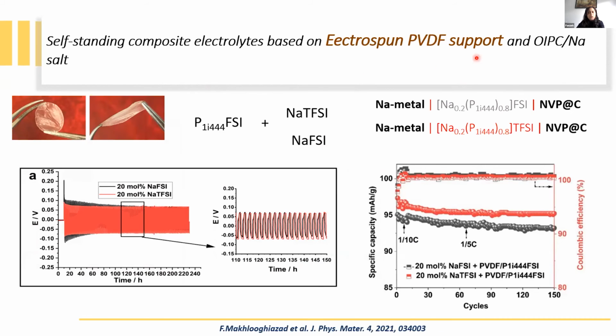So we tried to combine the plastic crystal that I mentioned mixed with sodium salt. We combined them with the electrospun PVDF support to make a freestanding composite electrolyte. So then we made this freestanding, self-standing composite electrolyte based on phosphonium cation plastic crystal mixed with sodium salt, the sodium FSI that has the same anion as in the plastic crystal. And also we mixed them with sodium TFSI that has a different anion from the plastic crystal. So in this case, we have mixed anion.